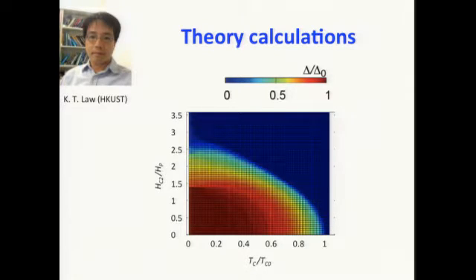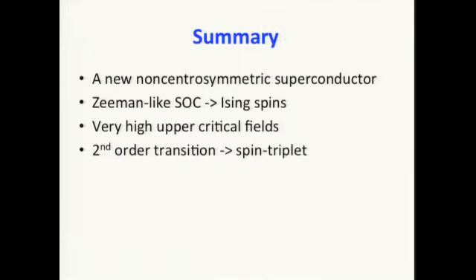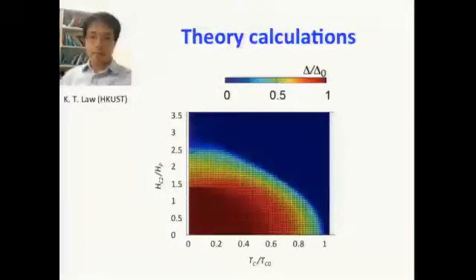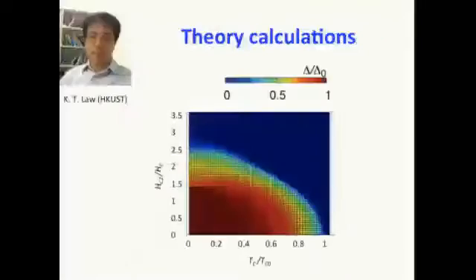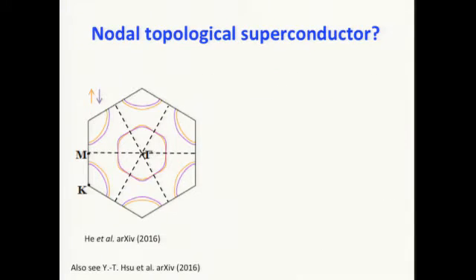In fact, in your band structures, there are multiple pieces of the band. So how should I think about which part is pairing to which? Actually, it's always pairing across the gamma point symmetrically. Let me go to the Fermi surface. Yeah, so this is the Fermi surface here. Basically, we have Cooper pairs from the gamma pocket, where any momentum at this point is coupled to the momentum at that point, as well as the K to K prime.